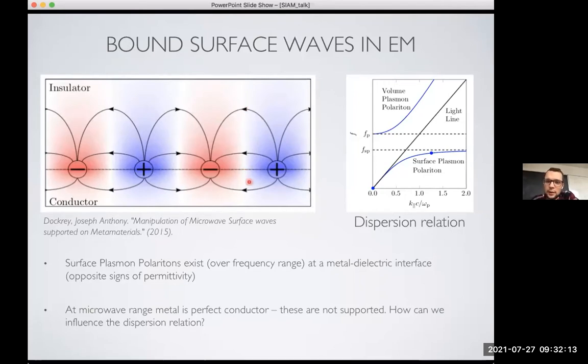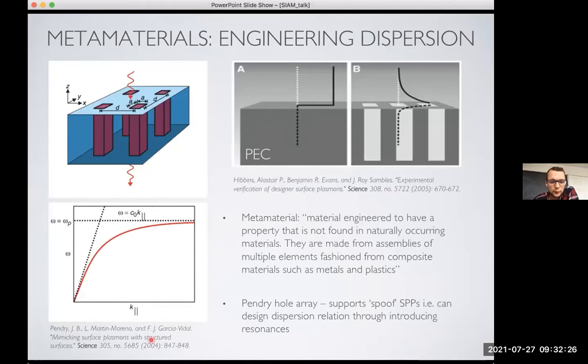So the main idea behind metamaterials then is, can we do something to the surface so that we can alter the dispersion? And that's basically what this whole talk is going to be about, it's about manipulating the dispersion relation to control surface waves. So in 2004, John Pendry, who's sort of seen as the godfather of metamaterials here at Imperial, he created this thing called the Pendry Hole Array, where he basically took a perfect electrical conductor, so it was like a slab of silver, and they drilled holes in it. And these holes were sub-wavelength and just a periodic square array. And what that did was it basically tricked the material into thinking that it can support a surface plasmon, and this dispersion relation here, you could now tailor it. So you could tune the frequencies and get down into the microwave regime. So by adding some structuring, we gave the material a property that it didn't have without the structuring. And that's kind of a very general definition of what a metamaterial is. It's an artificial, man-made composite structure that allows some behavior that wouldn't naturally occur.